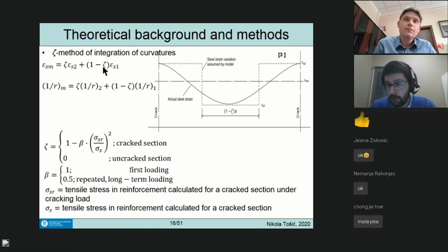And because we can do it to strain, that means directly we can do it to curvature as well, because it follows directly. So the mean curvature is going to be the Zeta distribution coefficient times the curvature in the fully cracked state, and 1 minus Zeta times the curvature in state 1.